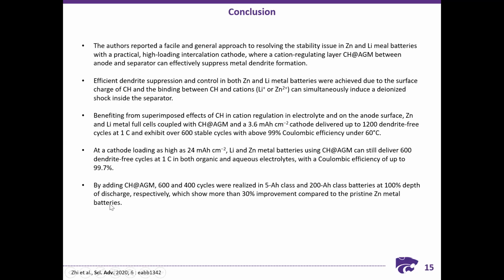As you can see from the preparation, they just dip the AGM for a few seconds. So I don't think they have done such control experiments, because what you need is a thin layer of CH, and you need to impose the negative surface charge on the interlayer. That is their goal, and it has been achieved with very few seconds of interaction between the AGM and the CH solution.